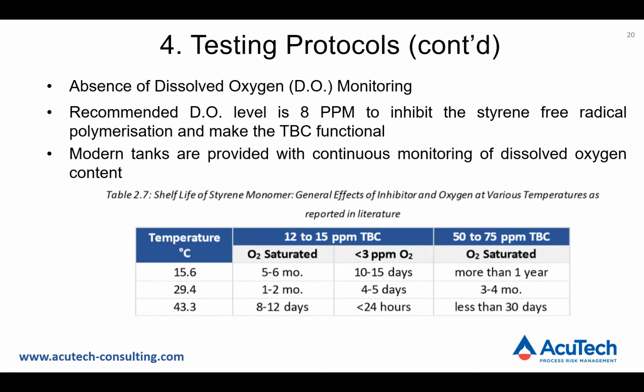Unfortunately, there was no monitoring device or monitoring system in place to measure the level of dissolved oxygen in the styrene monomer tank, in the M6 tank, or in any of the other styrene tanks at the facility. This is not acceptable as dissolved oxygen is a critical input to the effectiveness of the inhibitor.